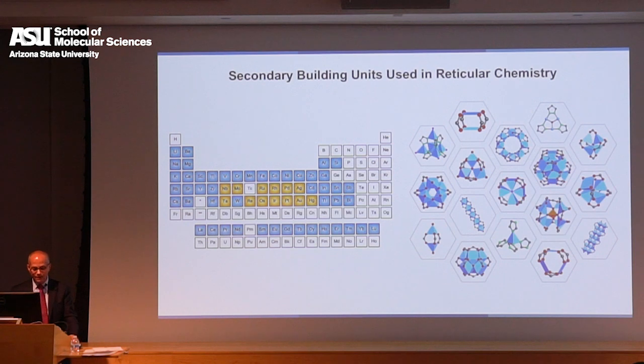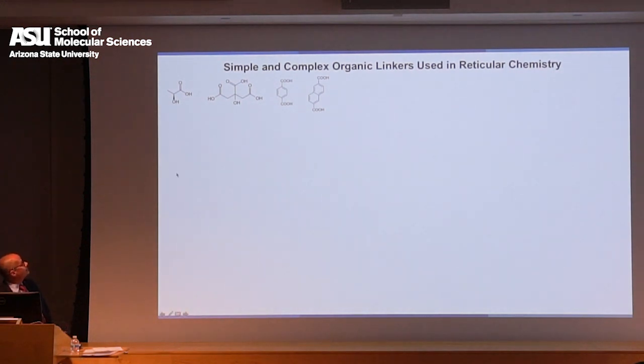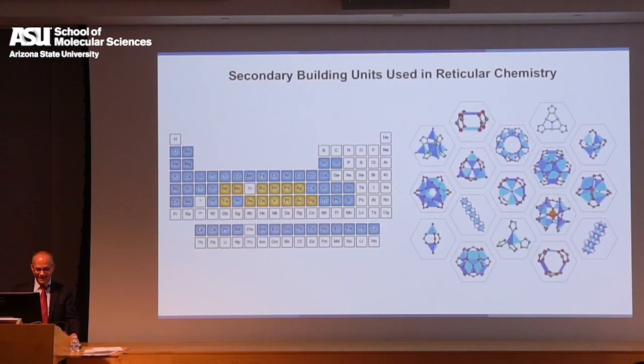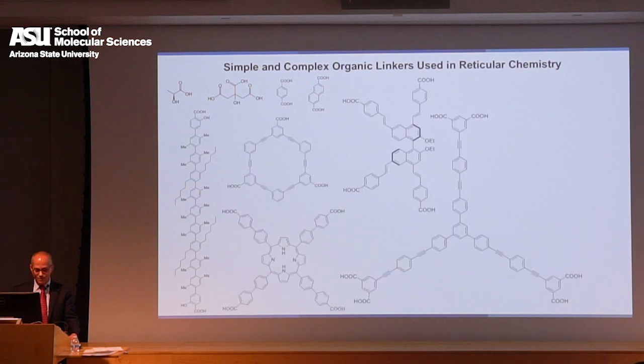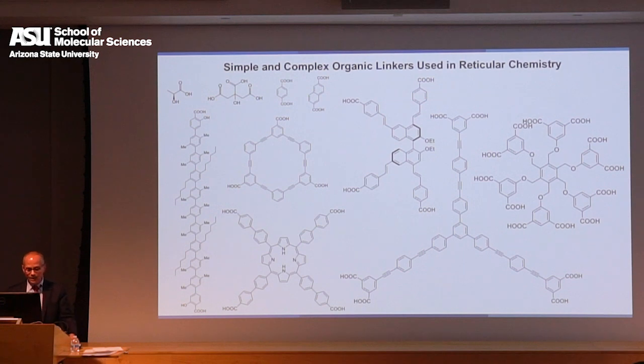Well, it didn't take Mike very long to recognize that basically any building unit that you could get your hands on, which could be a geometric unit, can be linked together into a network that he had described in his book, the Yellow Book, that was already published when I joined ASU. So we could take linkers that are benign, such as citric acid or terephthalate, lactic acid, and make MOFs out of them. So you can make MOFs that are edible. They've been eaten by some of Stoddard's students. And you can make MOFs from the most exotic linkers. So what this meant is that any linker, any cluster that you can get your hands on, you can make it into a MOF.